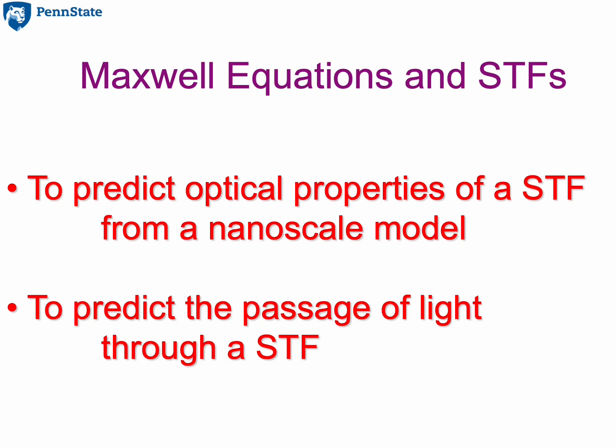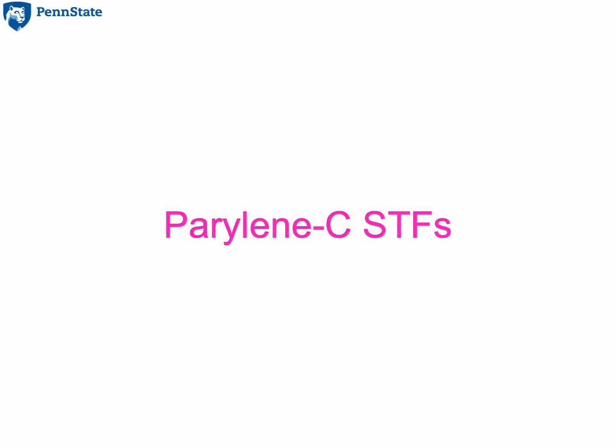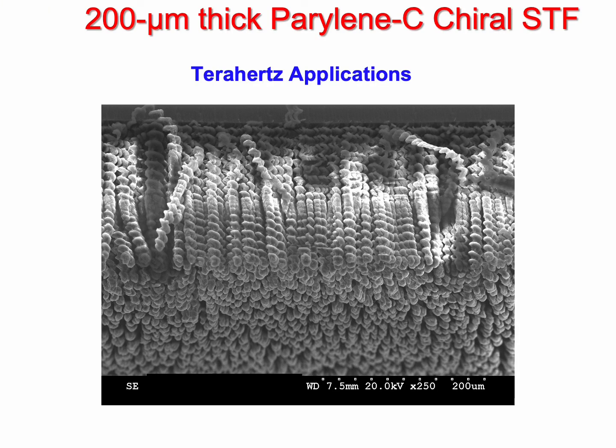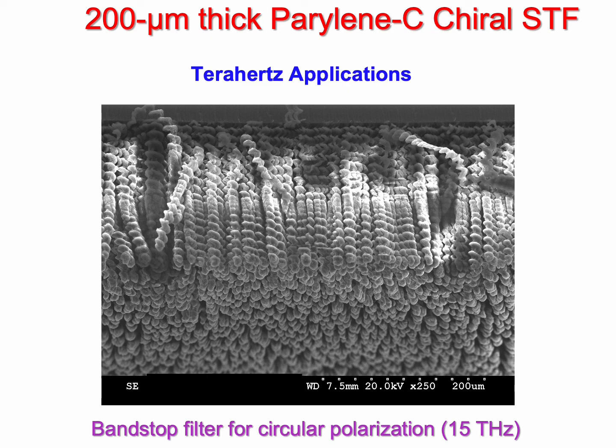A recent development towards multifunctional sculptured thin films is the fabrication of these materials made of parylene C, a polymer approved for human implants by the Food and Drug Administration. My students have used a physicochemical evaporation method to produce a chiral sculptured thin film with a period of about 20 micrometers. This can serve as a band stop filter for circularly polarized electromagnetic waves at about 15 terahertz frequency.